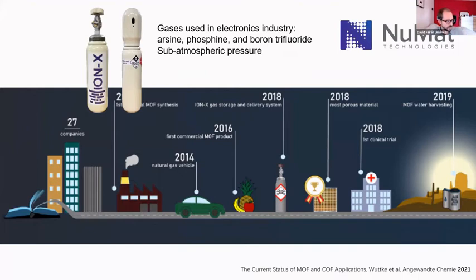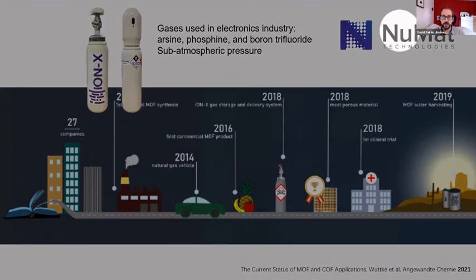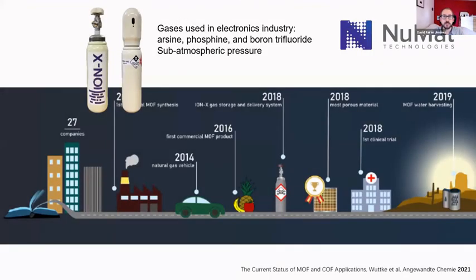The second big product that was created is Ionx. This is from a company from Northwestern University, NUMAT, a spin-out from Northwestern University. And this was using the MOF to store gases that are used in the electronic industry, okay? Really, really toxic gases, okay? Like arsine, phosphine, boron trifluoride, basically quite toxic, okay? They store this at 700 torr. And this is good because if there is an accident, these gases will not be released from the material, okay? They also have some problems because these gases start reacting with the MOF when they wait about 6 months or so, okay?